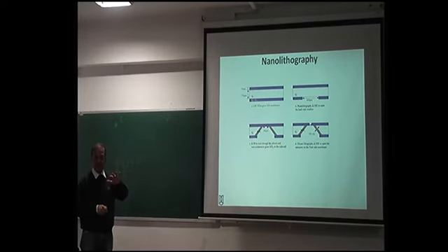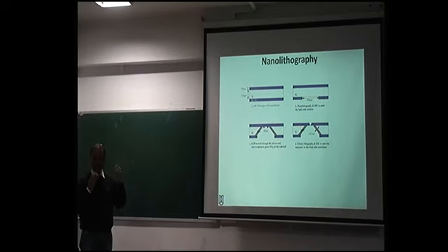So there are 4 steps. Take silicon, cover it with silicon nitride on both sides with a CVD. They have used LPCVD, but you can use any CVD actually. And then create a window. Silicon nitride can be etched by reactive ion etching, so create a window. Through that window, you let in KOH. KOH will etch out this portion of the silicon.